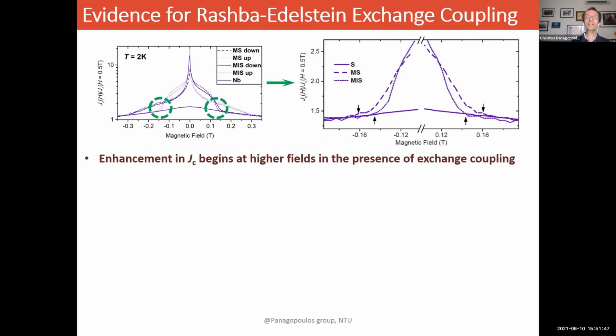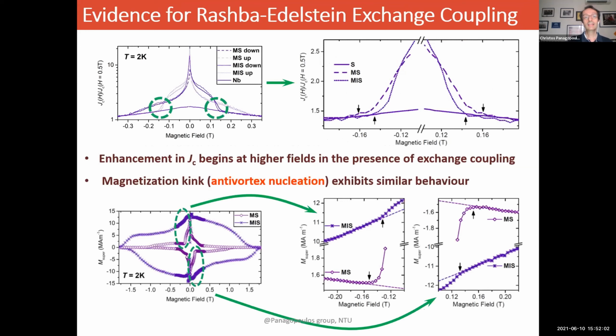And indeed, what we find is that when we look at the critical current density of our heterostructure, there is an enhancement in the critical current, which begins at fields which are higher when you have exchange coupling. And the magnetization kink, which indicates anti-vortex nucleation, exhibits a similar behavior. So that points to the fact that indeed, when I have the right size of skyrmions, and I am close to my superconductor, then I do have Rashba-Edelstein exchange coupling.